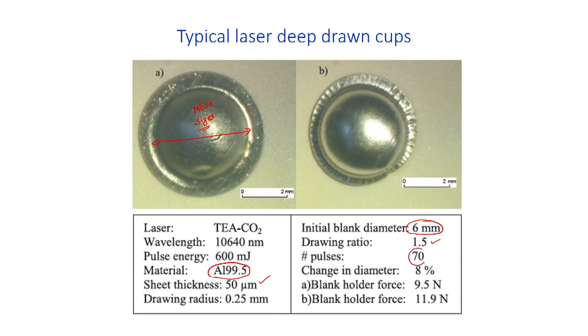The number of pulses was 70, and the pulse energy was about 600 millijoule. Here a CO2 laser was used, and the wavelength is about 10 microns. To hold the foil, or the worksheet, at the die, a blank holder force was applied of about 9.5 Newton. This is in case of A, where we applied 9.5. In case of B, it was slightly increased to 11.9 Newton. So, successfully the cups were drawn by using laser based deep drawing operation.